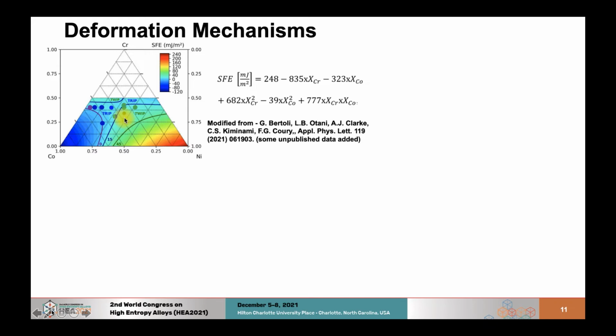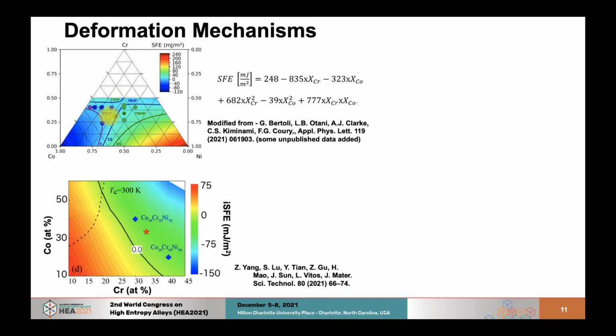And what we basically observe, all these dots here are experimental alloys, is that the trend seems to follow more or less what we see for steels. So when the stacking fault energy is between 15 and 45, we tend to see a lot of TWIP. This does not mean that it's TWIP exclusive, but what we call here TWIP dominated, when we see a lot of deformation twinning. And when we go to a lower stacking fault energy of 15 and below, we start having much more TRIP, so transformation to the HCP phase. This is also well shown by DFT calculations. So a similar trend is observed for the intrinsic stacking fault energy. This paper derives relations for other stacking fault energies. I recommend reading it for more details.